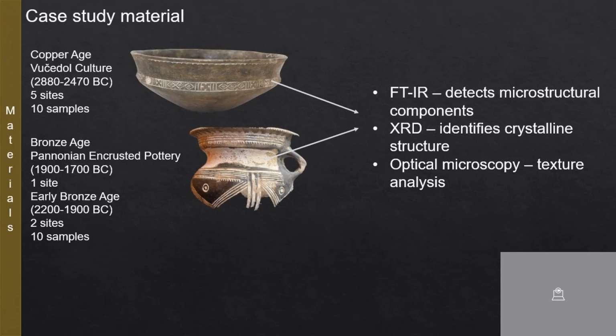To determine the raw material used for inlays, 20 decorated vessel samples were examined, 10 from late Copper Age and 10 from early and Middle Bronze Age. These samples came from 8 archaeological sites across Croatia. Complementary analytical methods were applied: X-ray diffraction to identify crystalline structures, infrared spectroscopy for microstructural components, and optical microscopy for texture analysis.